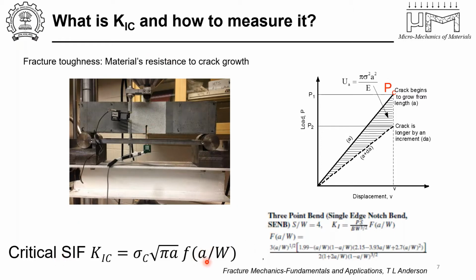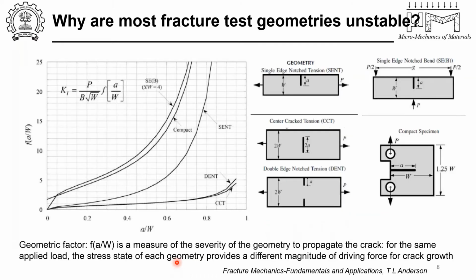And the geometric factor for a 3-point bending beam, which looks like this, is a complicated formula that is obtained either using numerical solutions or analytically if it's a simple configuration. So basically, for measuring fracture toughness, you need a simple configuration whose stress state, the far field applied stress state, is well known, and the initial crack length is also well defined.